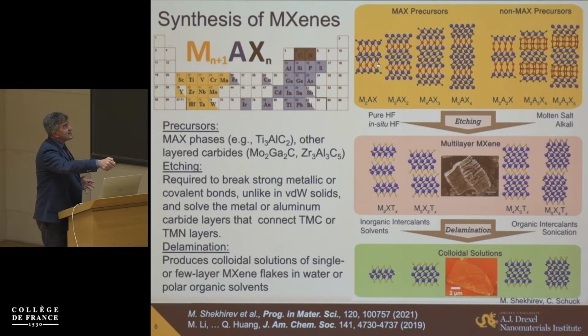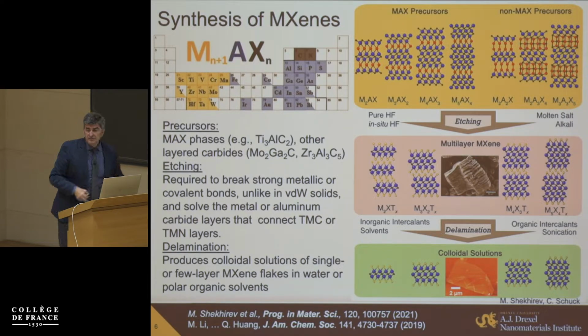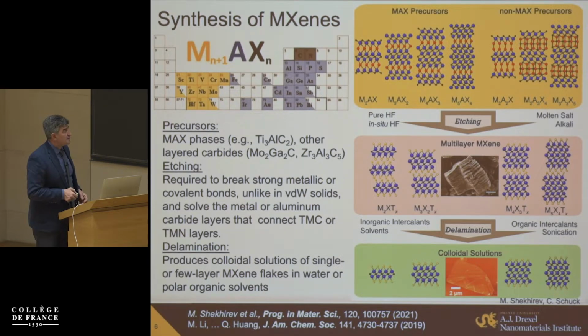And we selectively etch the monatomic layers, or few atomic layers, connecting the carbide and nitride sheets away. Before, there were strong metallic covalent bonds, and you cannot break them by simply mechanical delamination, unlike in graphite or molybdenum disulfide. So you need to etch them. But then you end up with oxygen, OH, fluorine, other terminations on the surface, and there are now weak van der Waals hydrogen bonds between the layers, so you can delaminate the structure, just as you would delaminate or exfoliate graphite or molybdenum disulfide.